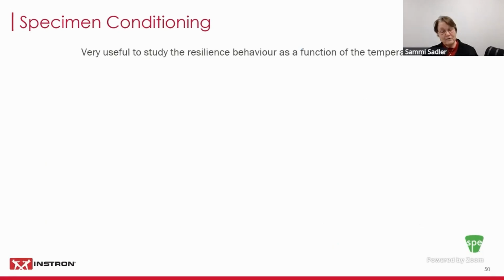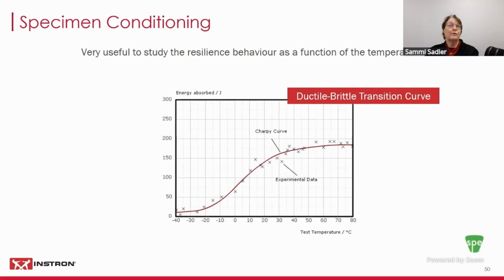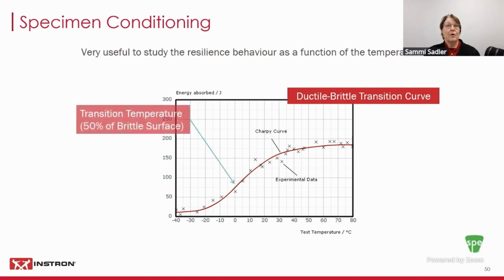Another thing to pay attention to, we find 20% of customers testing with a pendulum condition their samples. So they are looking for that ductile to brittle transition curve. And so how you condition and how you handle the sample after it's been conditioned. So what you are doing to move the cold sample into the pendulum can come into play. So as we know, we look for where we go from a ductile to a brittle.